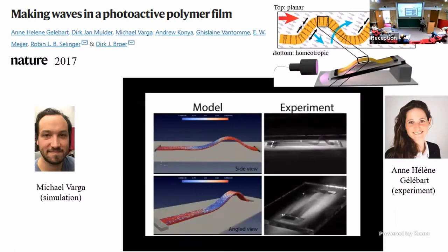So here's the experiment. I have a thin piece of nematic elastomer. It has the nematic director pointing parallel to the long axis of the film on one side, and then perpendicular on the bottom, what we would call homeotropic anchoring conditions. So planar on the top, homeotropic on the bottom.